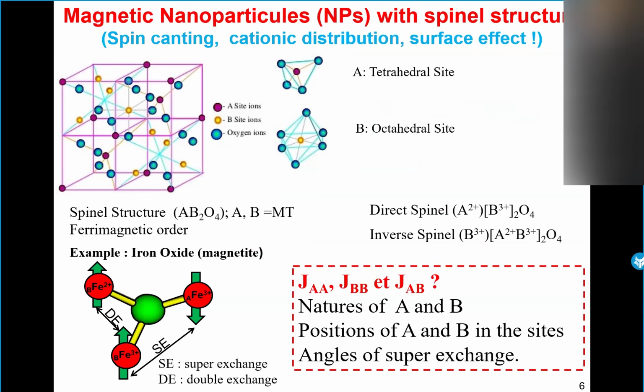The spinel structure was presented by Jean-Marc. Here, for example, for iron oxide and different cobalt spinel structures, the exchange interaction between ions is indirect exchange, of type superexchange or double exchange. The exchange integral between ions depends strongly on the nature of the atoms A and B, but also on the positions of atoms A and B in the sites, and the superexchange angles. That means changing any of these parameters gives new physical properties. So it is a very rich system for study and for application.